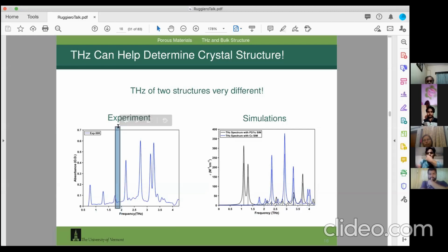So this result is still not good, and we're still optimizing what theory we use, and this is very preliminary, but it just goes to show you how sensitive this tool can be for structural identification. So even with X-ray diffraction, which people would say is kind of the gold standard for structure, this highlights that in some ambiguous cases, terahertz is useful.